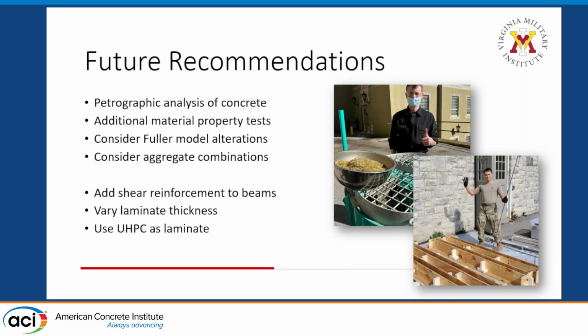So future recommendations. Again, this was really an initial phase of this project. First was a petrographic analysis of the concrete. This is what we wanted to complete, but we were running out of time with the semester ending. We were hoping to take a petrographic analysis of each sample and calculate how much air voids was within each of the mixes to see how much each mix was able to pack and decrease the air voids, and then correlate to the resultant compressive strength as to why certain mixes were stronger than others. Additionally, we wanted to do some more material property tests like the tensile strength test, modulus of elasticity, and the Poisson ratio to garner further information on the other samples.